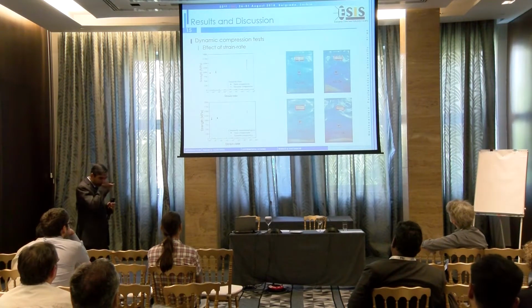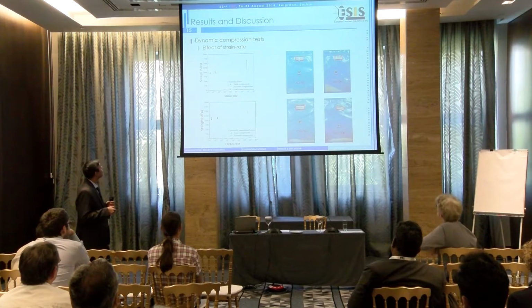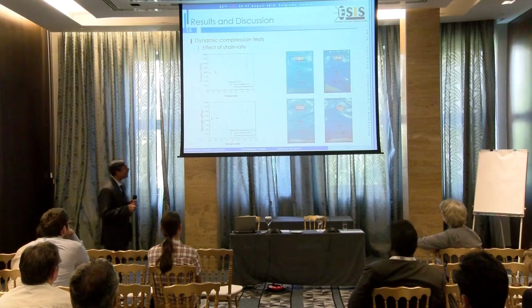Another important effect is we have to see whether they are rate sensitive or not. So we have plotted the compressive strength values against the strain rates. This result shows that both glasses are rate sensitive. And also we have collected the glass debris after the test.